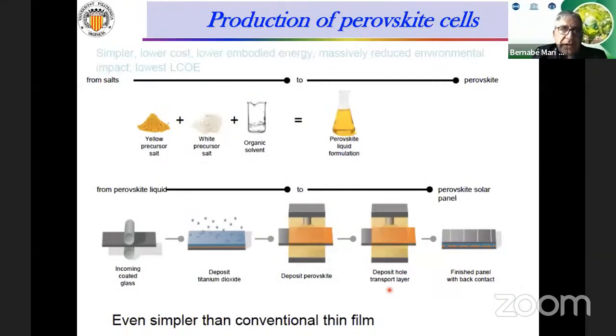Well, compared with silicon, the procedure to obtain perovskite solar cells is quite easy. We mix the precursor salt with an organic solvent, and we have the perovskite liquid formulation. Then we deposit this on a substrate, by roll-to-roll, spin coating, or inkjet printing, and we are able to obtain low-cost solar cells with good efficiency.